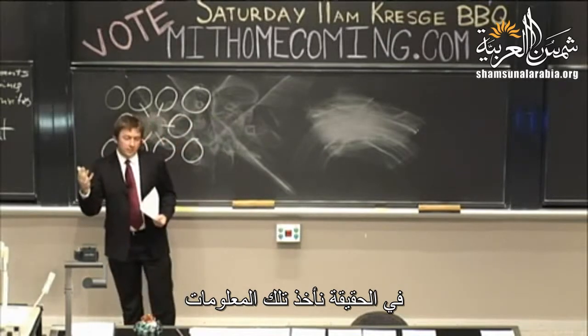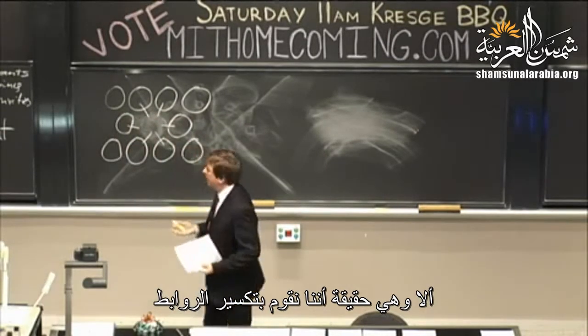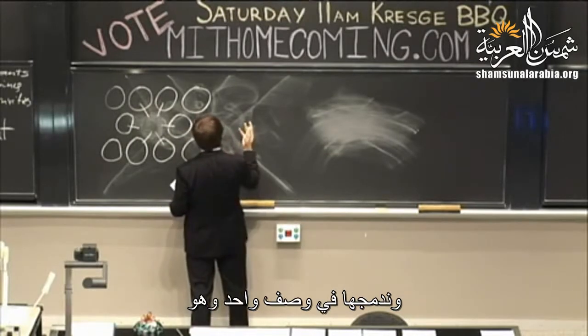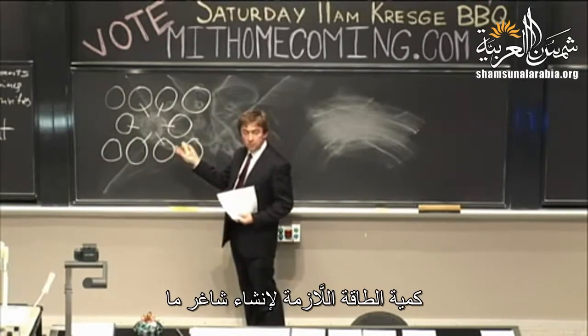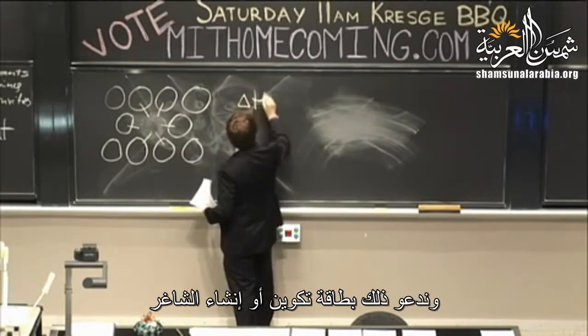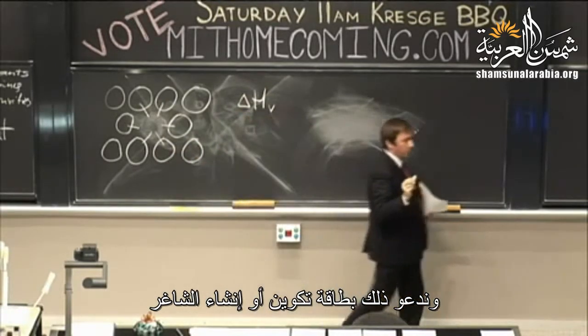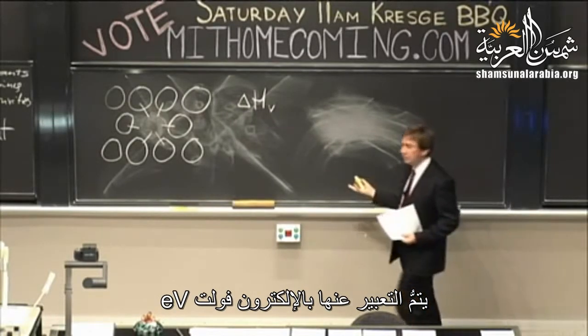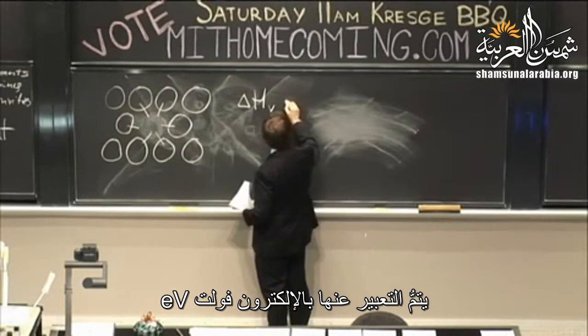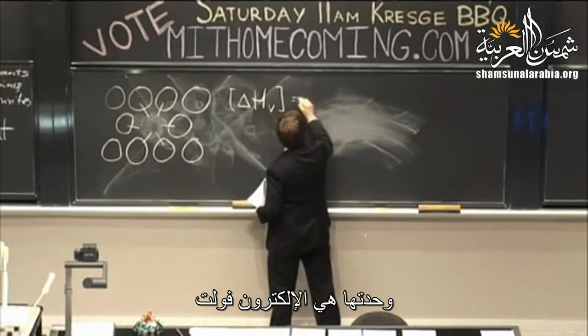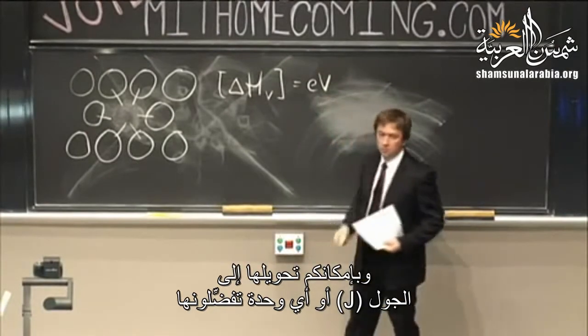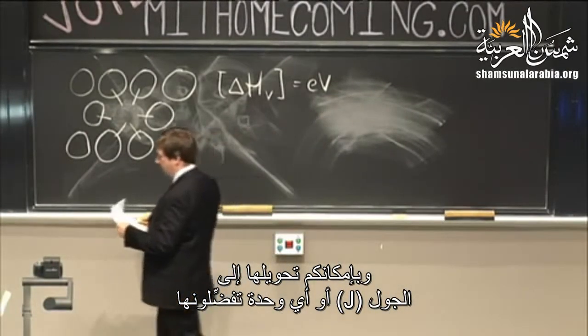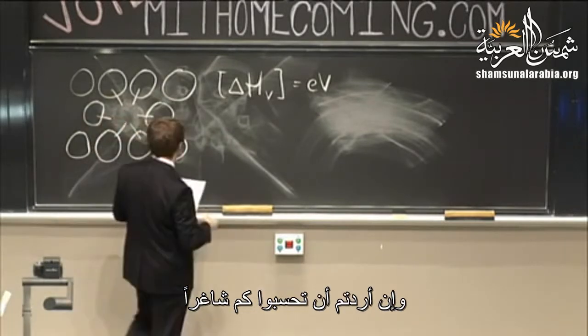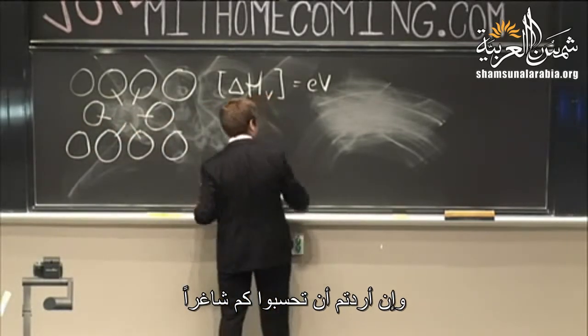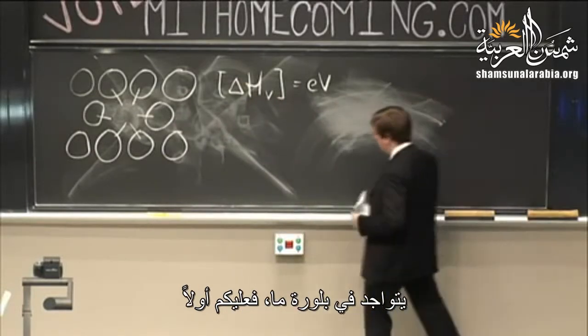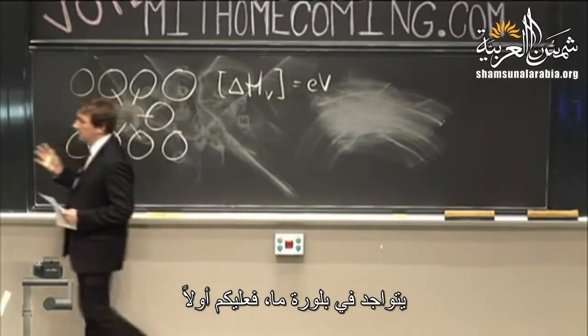So we actually then take that information, the fact that we're breaking bonds, and encapsulate it in a single description of how much energy it costs to create a vacancy. And we call that the vacancy formation energy, right? So this is an energy, and so it's expressed in eV. Its units are electron volts. You can convert them to joules, obviously, anything you like. And if you wanted to then compute how many vacancies there are in a given crystal, well, first of all, it